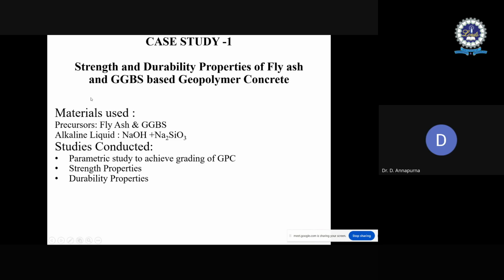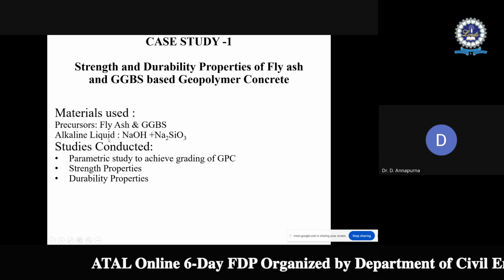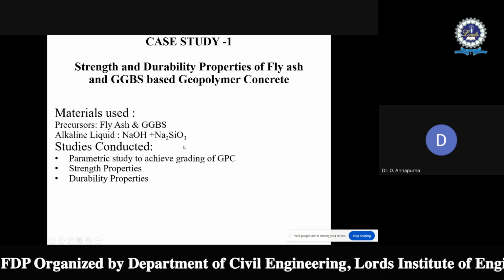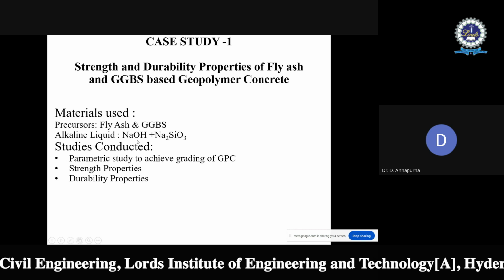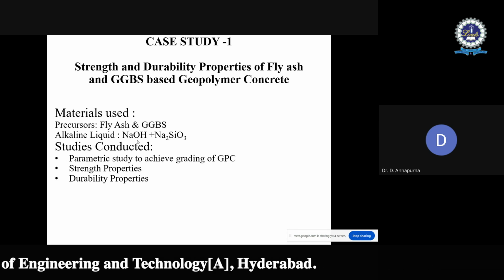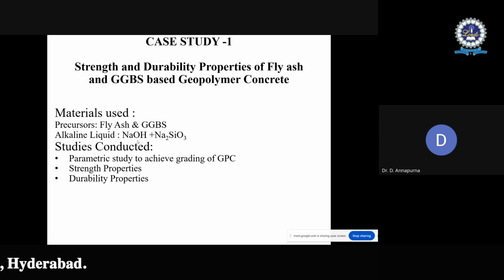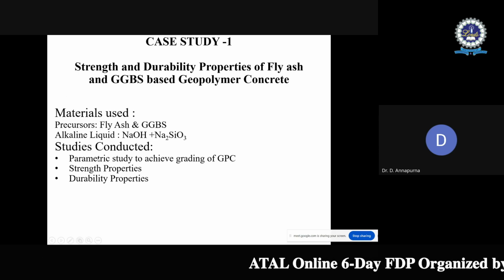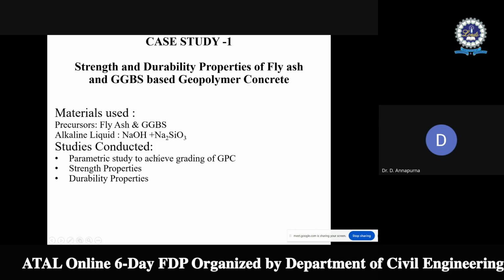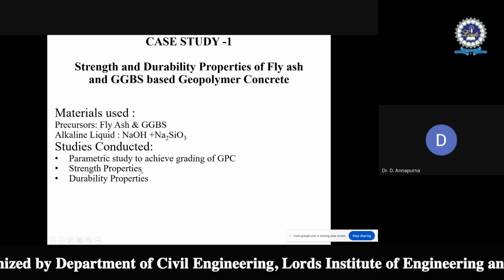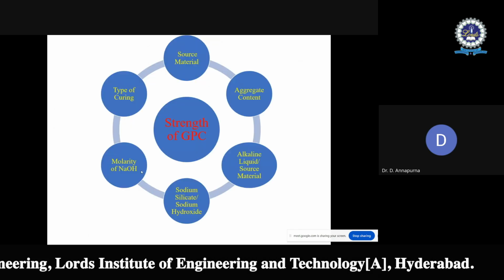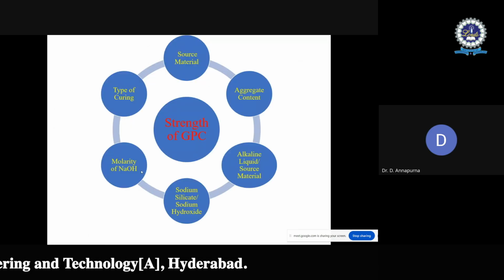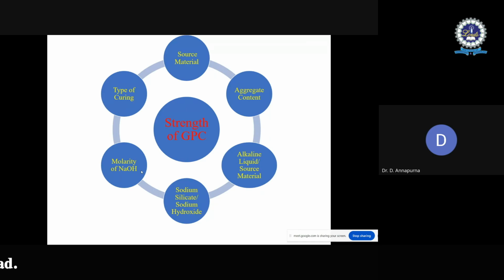In this particular work, the precursors are fly ash and GGBS. The alkaline liquid is a combination of sodium hydroxide and sodium silicate, because compared to potassium based alkaline activators, sodium based alkali activators are more reactive in nature. That is the reason only sodium based material was used in this work. A parametric study was conducted to achieve grading of geopolymer concrete, then the strength and durability properties were studied. To begin with, the mixture proportions of geopolymer concrete were done using the guidelines given by Rangan.